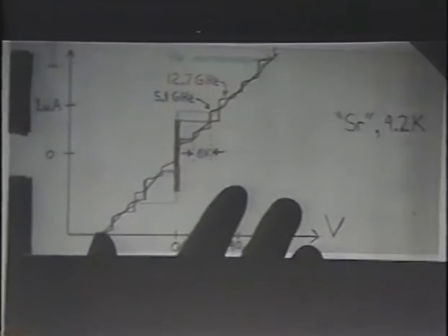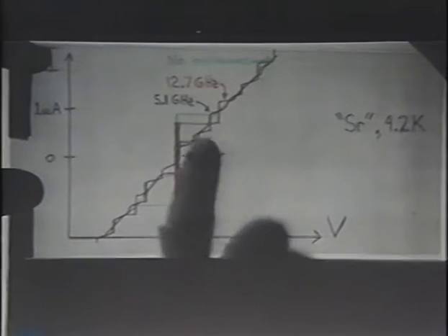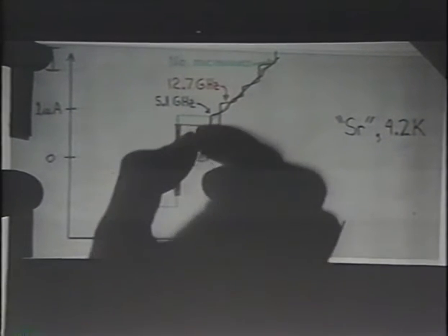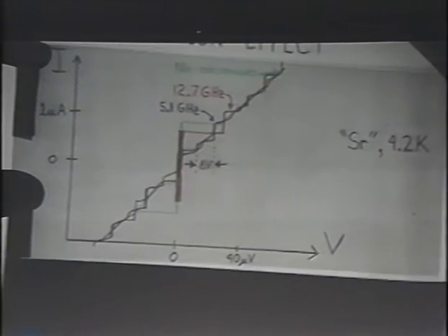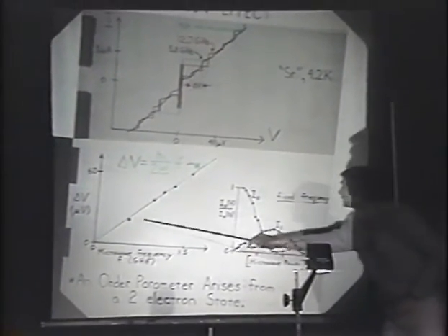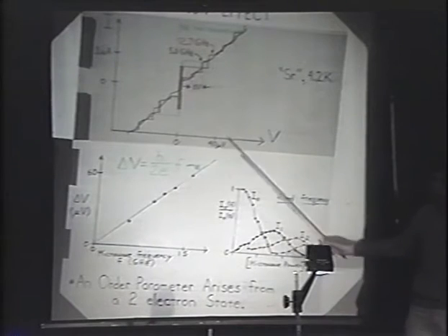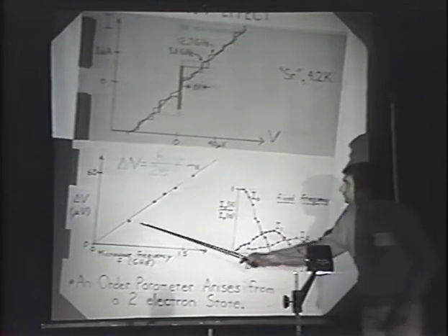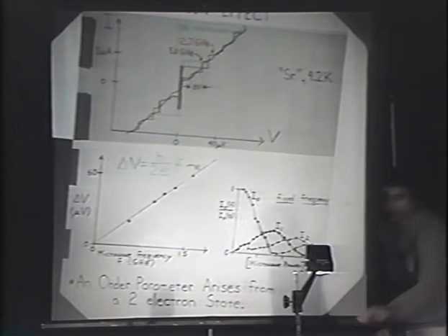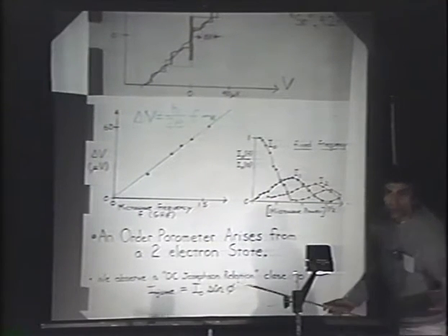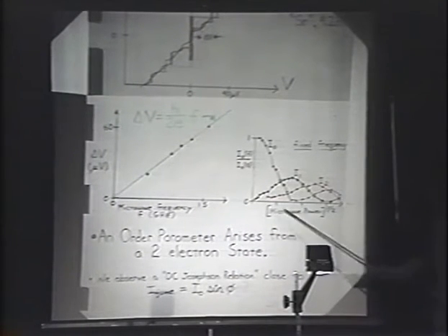At 5 gigahertz, we see this. What we do is measure the separation of the steps versus frequency. I plotted that in the points right here. And the prediction for h over 2e is given by the green line, and we see excellent agreement. This, of course, says that the order parameter arises from a 2-electron state in this superconductor.